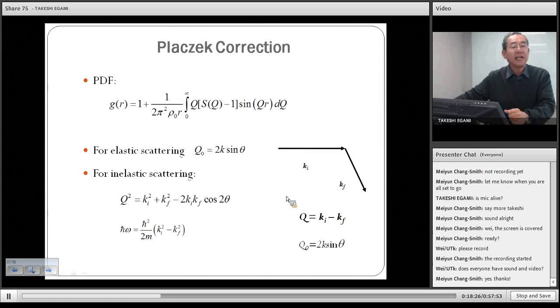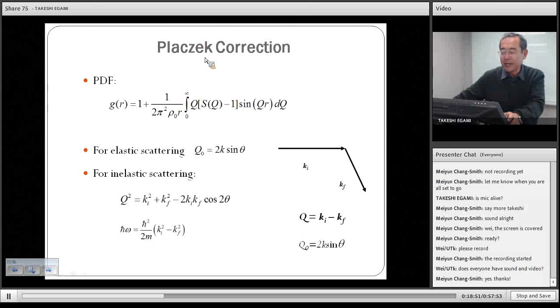So first thing that I'd like to point out is so-called Placzek correction, and this is a standard procedure used in the PDF package. If you use a PDF package, there's a choice of Placzek correction. And to make the long story short, I recommend against using Placzek correction because it does correct something, but actually the damage is larger. So I'll discuss why it doesn't work.